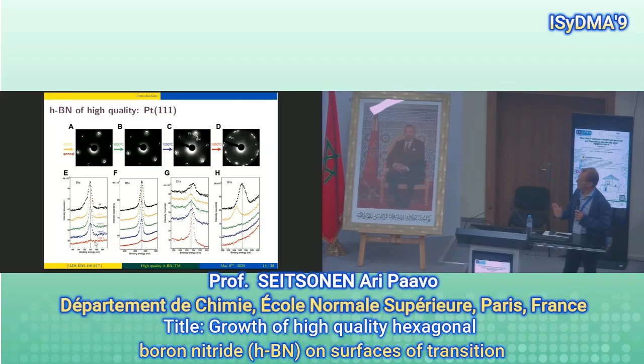So we see different binding energies in the core orbitals depending on the chemical state that the atoms are in. And this is specific for different elements. Usually they are different energies, so you see that the energy scale is completely different. This is boron, nitrogen, carbon, and oxygen. And you see the signal at the specific energies. Here one was just interested in how much of these elements there are on the surface, so not in which chemical state they are. And the colors are the same as here, so the annealing temperature. So one starts from the initial one, that's the black one, and then when one heats it up, the curves are just displaced toward the bottom. So the highest annealing temperature is the red one at the bottom.